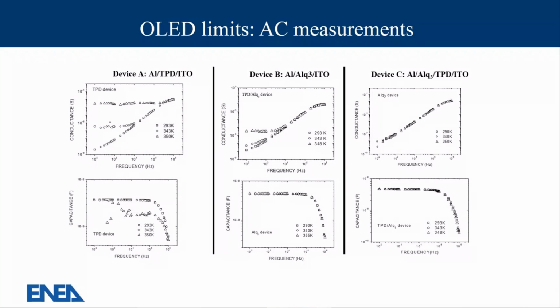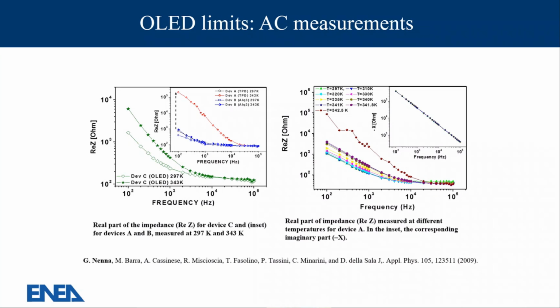If we pass the glass transition, it appears that there is only the resistance due to series resistance, and in such a way the contact on the top will start to find some way also to conduct directly with the one on the bottom. It's possible to see this kind of mechanism changing, of course, the temperature, with higher temperatures than the ones I showed before. If we take care only of the real part of conductance, we see that all will go at high frequency altogether to the series resistance.